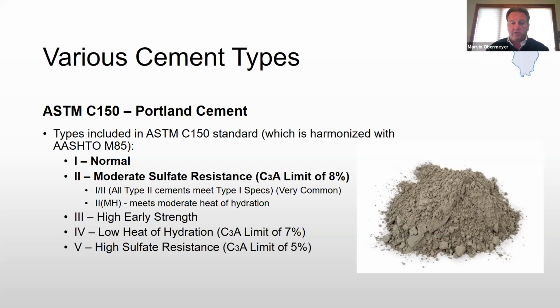And type 5, which is also very rare, is high sulfate resistance. Now you'll notice type 2 is moderate sulfate resistance, type 5 is high sulfate resistance. Sulfate resistance usually has to do with wastewater treatment plants or sulfates in the soil. Those are usually the two situations we see there. If you take a type 2 and blend it with a fly ash or a slag, you many times can achieve high sulfate resistance results. So that's what a lot of the guys do when they have a type 5 application: they'll blend it with a fly ash or a slag.